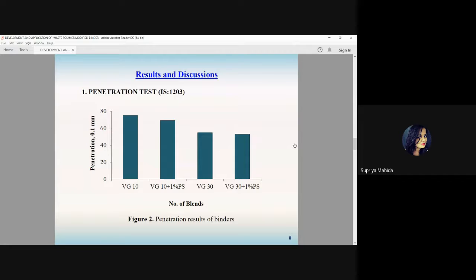So after having a proper homogeneous mixture of these two kinds of modified binder and conventional binder, we went through the physical parameters to find out what happens after addition of thermocol in conventional bitumen. So first we performed the penetration test. The procedure we followed is as per IS 1203. The penetration generally shows the hardening of the binder.